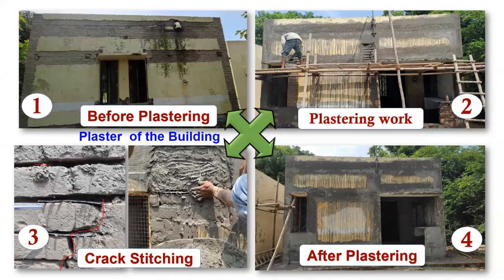So we made a slot and placed the textile. And we used a latex modified slurry. We pasted it like this and filled the cracks. And then we went for fresh cement plastering, because I want to maintain the level very perfectly to distribute the force through the textiles.